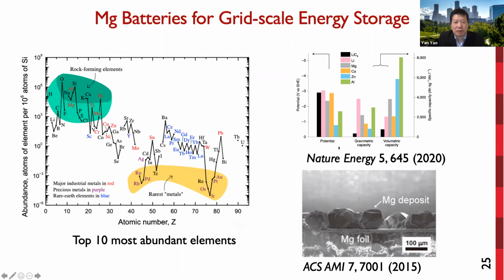So in our recent review published in Nature Energy, we reviewed the current status of the multivalent metal-ion battery research, and provided a roadmap for future development. So among many metals such as magnesium, calcium, zinc, and aluminum, magnesium battery is considered one of the prime candidates. The direct use of magnesium metal as anode is important. Magnesium metal has a reputation of dendrite-free plating as compact crystals. So this is in sharp contrast with lithium metal growth behaviors. However, in recent years, reports have shown magnesium also forms dendrites when the electrolyte is not fully optimized to have the highest Coulombic efficiency.